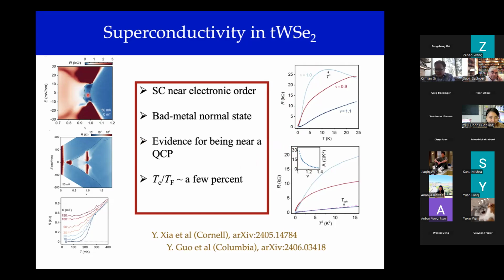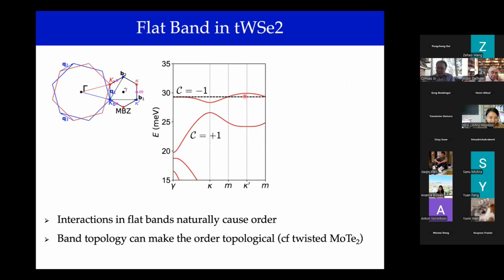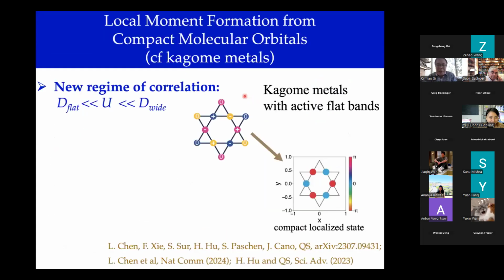So taking this phenomenology into consideration, but also this perspective that the flat band naturally breeds electronic order, we've looked at this problem from the perspective of analogy with something like kagome metals with active flat bands, in which I already mentioned in the introduction that if you have two kinds of bandwidth with a hierarchy between them, you open up a window of interactions that's in between. And so now one could consider this destructive interference, taking that seriously, that would lead to something like a blob, a molecular orbital, except that's not a very good representation. It's not orthogonal to the ones coming from neighboring unit cells, and it's not even complete.